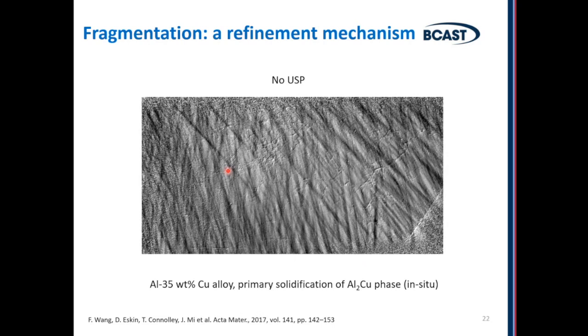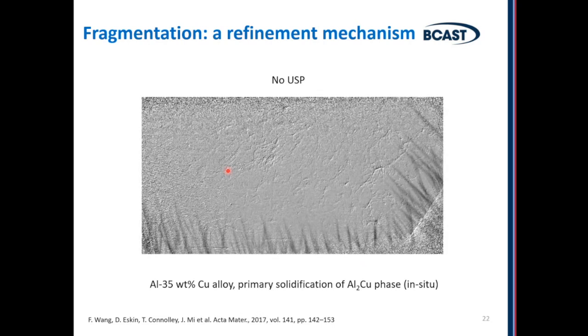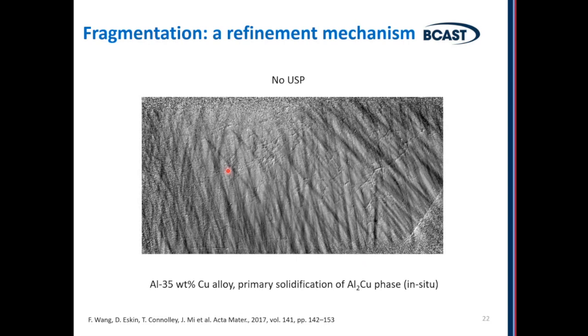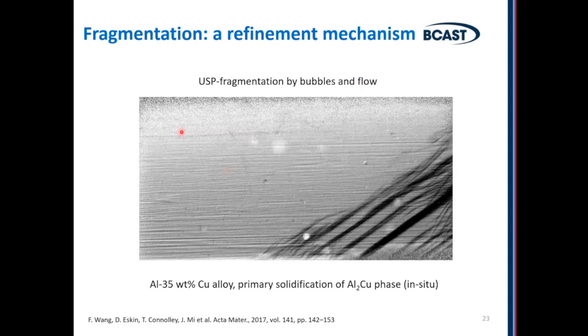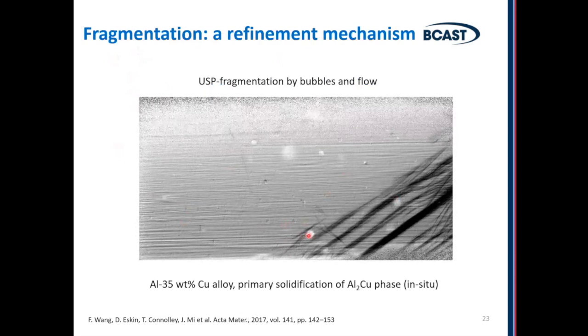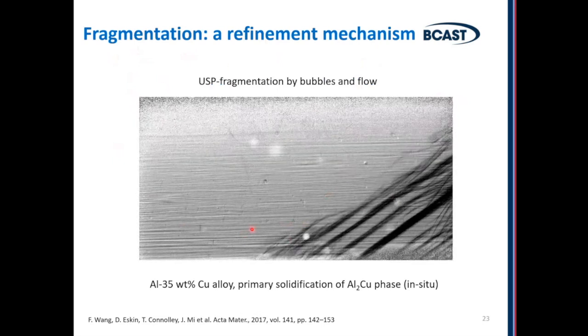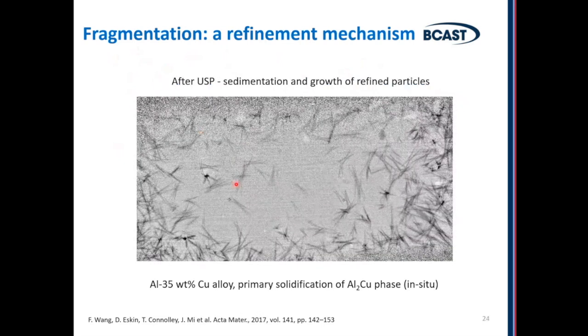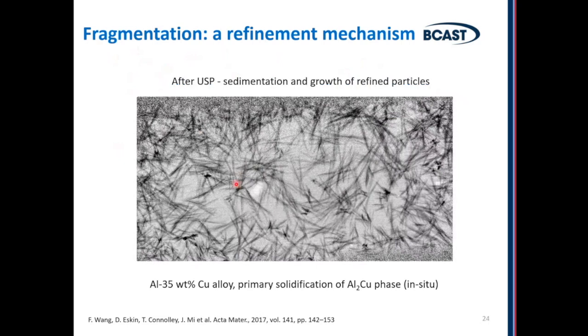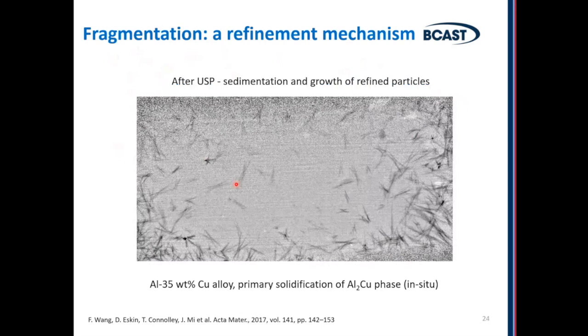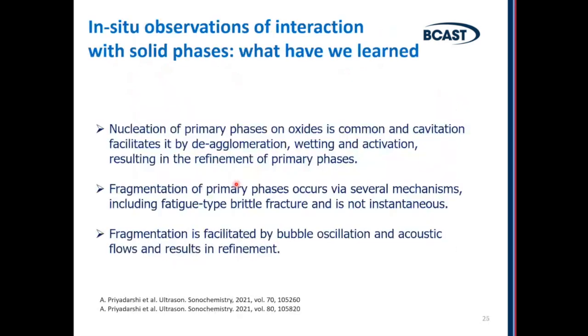This is an example of an aluminium-copper alloy in synchrotron. Without ultrasonic processing, you can see that there are huge elongated needle-like intermetallics formed. When you do ultrasonic processing, with the ultrasonic source here, the flows detach some of these intermetallics and bring them back into the cavitation zone. We don't see the cavitation zone in this frame, but they are going to the cavitation zone here. And then when you switch off ultrasound, that's what you have. These are fragmented intermetallics that sediment and create a much finer structure. And that's what happens also in real alloys when we process them with ultrasonic cavitation. So we learned a lot from these in situ observations. Some of these observations are quite unique to date, and we continue to work in this area. It's a very scientifically rich area of research.